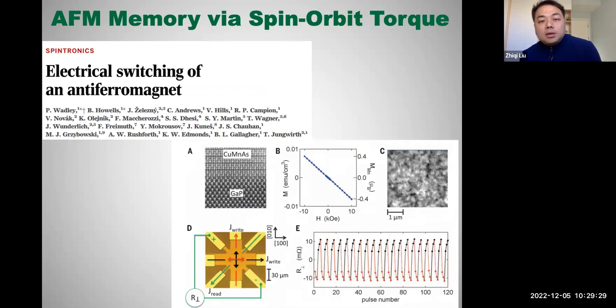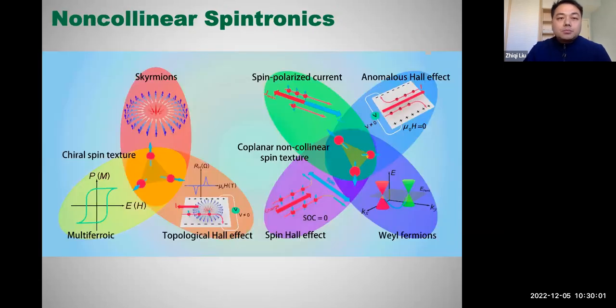In 2016, Prof. Yang's group, again, started to work on a new material, so-called copper manganese arsenide. They used electrical current to generate so-called Néel spin-orbit torque, an electrical approach to control the antiferromagnetic spin axes. And finally, they could also get a room temperature memory by virtue of the AMR effect.